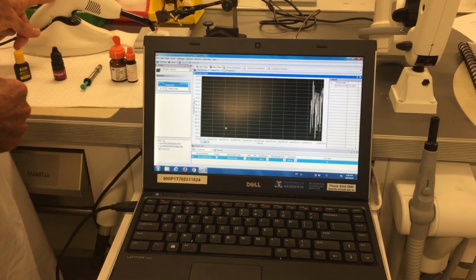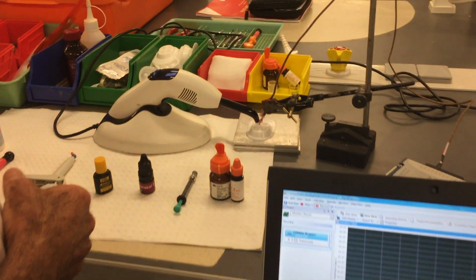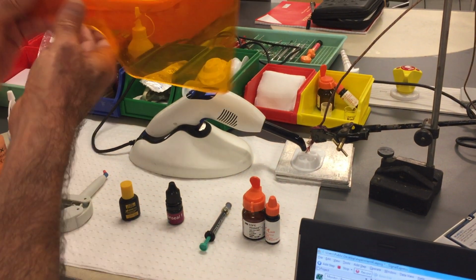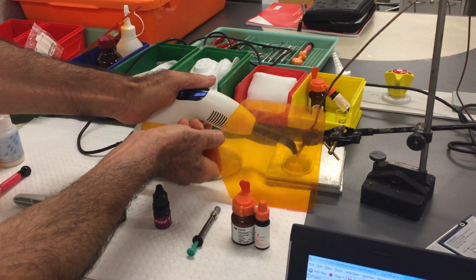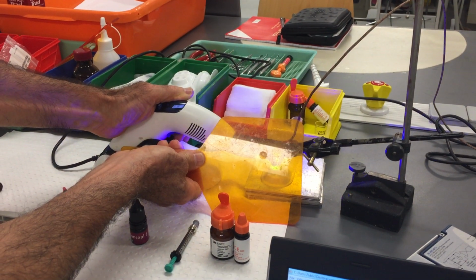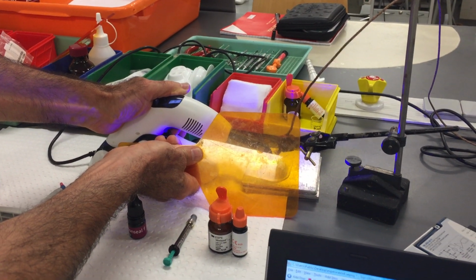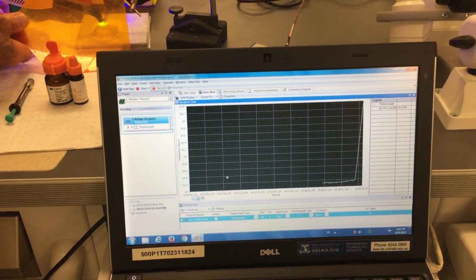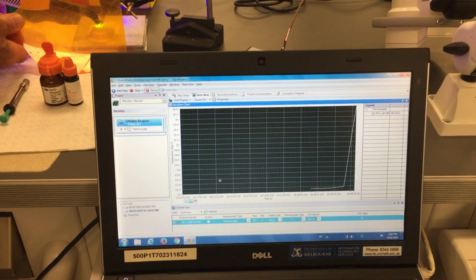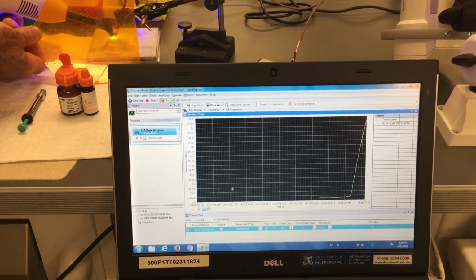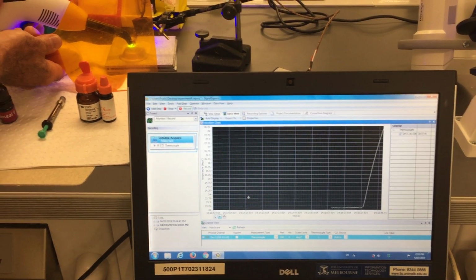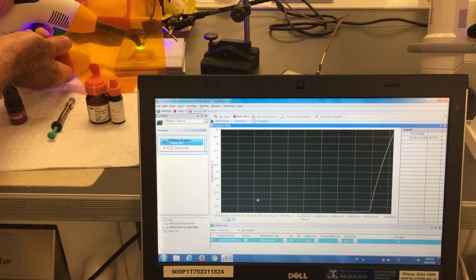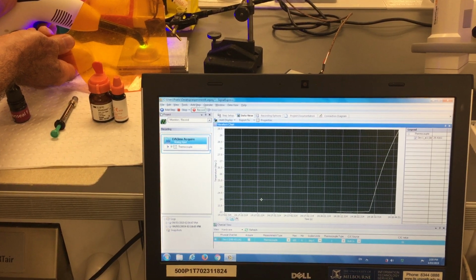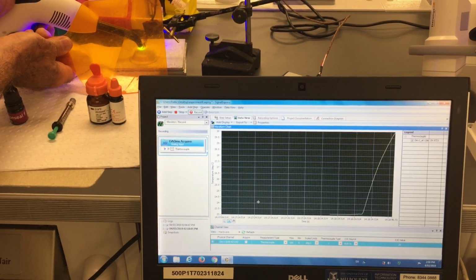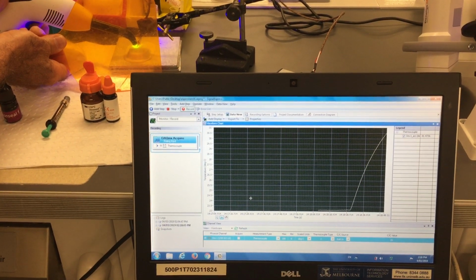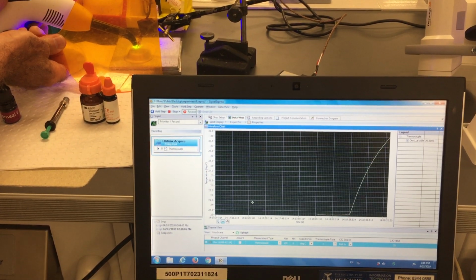We've got the lamp on high power, so if we turn that on, and it's on for 40 seconds, we can see the graph shooting up to record the temperature generated by the high power on the light curing unit. And at the moment it's shifting over up to 29, it's almost 30 degrees. So it's changed from room temperature up to 30 degrees.